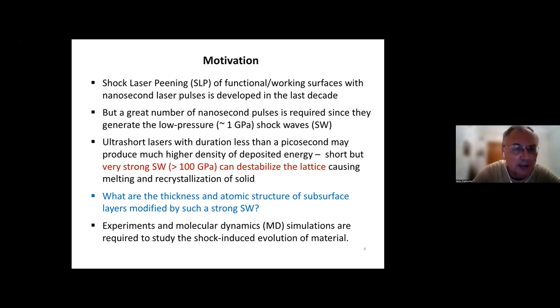By contrast, an ultrashort laser pulse with duration less than 1 picosecond may produce a much higher density of deposited energy. So a short but very strong shock wave, larger than 100 GPa, which means 1 megabar, can destabilize the crystal lattice and cause melting and recrystallization of the solid.